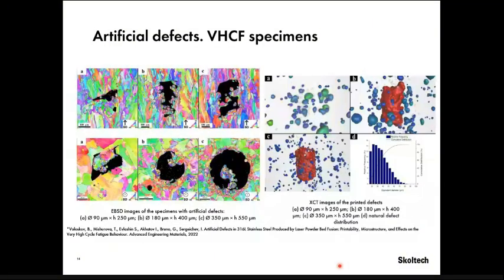And also we checked how it affects the microstructure, where we can see that artificial defects are surrounded by fine grains. It's related, first of all, to different contour parameters, and also to contact with the free surface. And computer tomography results. Here, one interesting thing: despite that in many cases, for optimization of our parameters, we got the smallest defect, which is like 90 microns in diameter,